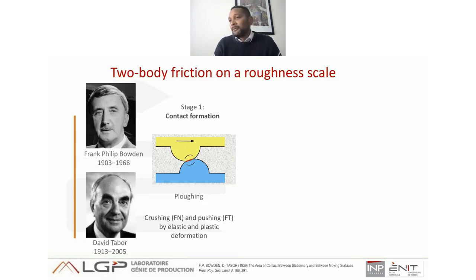In 1950, Bowden and Tabor proposed an approach to contact that has become a classic today. They proposed to explain the friction of two bodies at the level of asperities in the contact interface. This model is broken down into 3 steps. The first step concerns the formation of the contact. There are shocks and interpenetration of the asperities on the real contact area. Plowing then occurs. The normal force contributes to the crushing of the asperities, while the tangential force pushes them away. All this happens under the influence of elastic and plastic deformation.